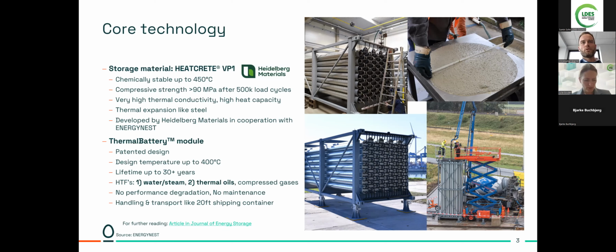It has a design temperature up to 400 degrees Celsius and a lifetime that can exceed 30 years. There's no performance degradation over the life, and as I mentioned, there's also no maintenance required on the core technology. The way it's designed allows it to be handled and transported as a normal 20-foot shipping container. Quite important is that we can use different heat transfer fluids to charge and discharge our battery. Notably, we can use water steam directly inside the pipes, we can use thermal oils, and we can in principle also use compressed gases.